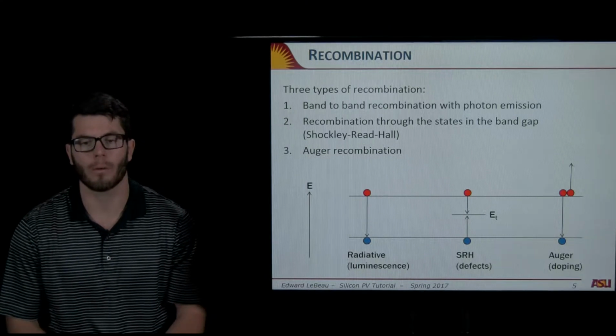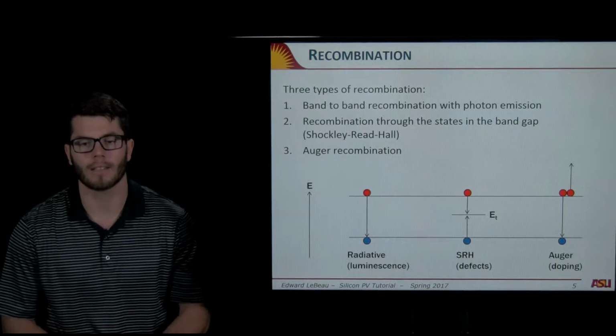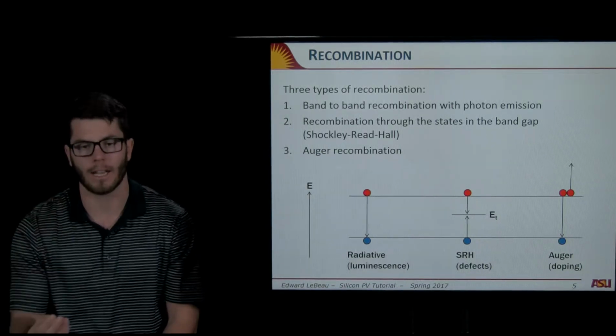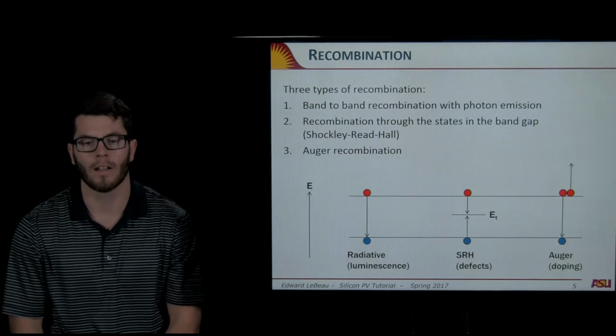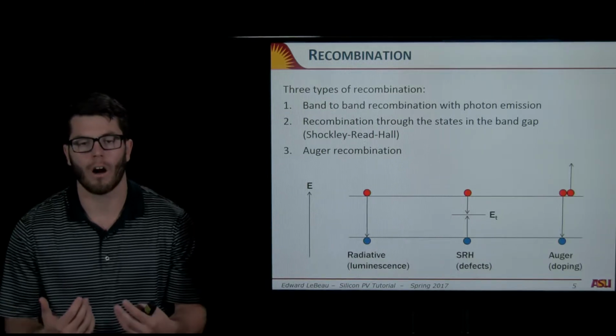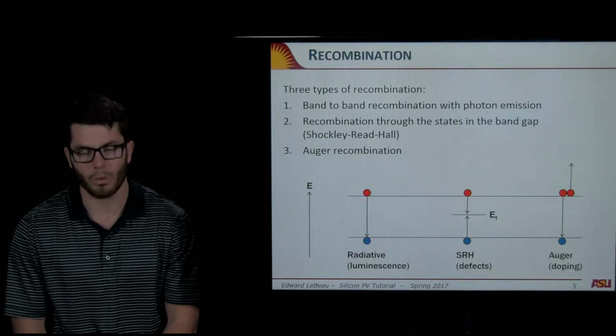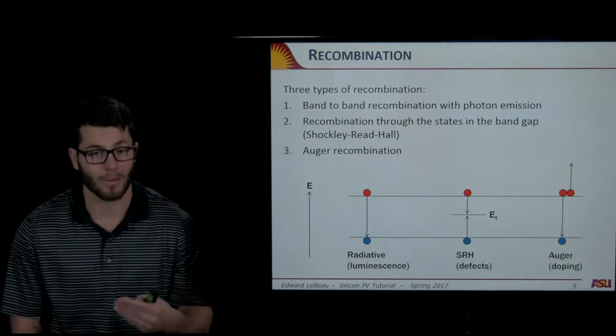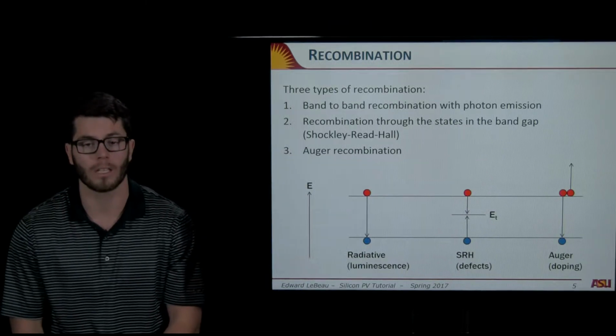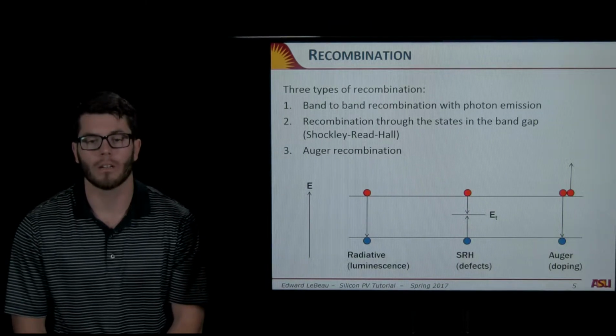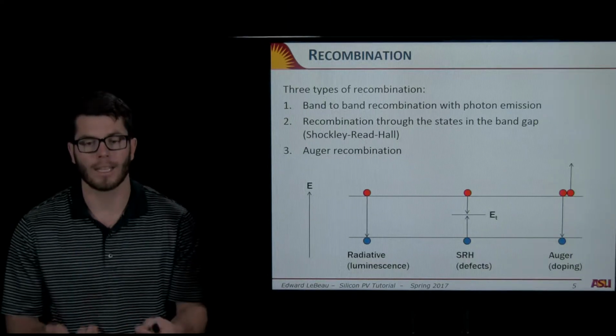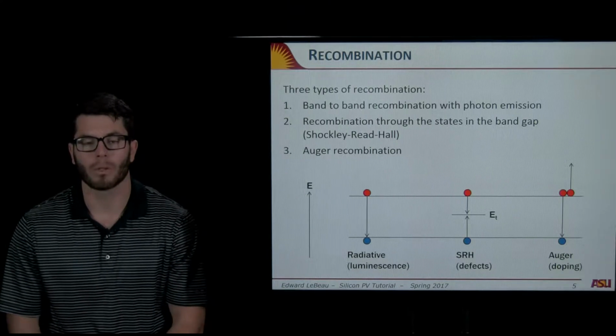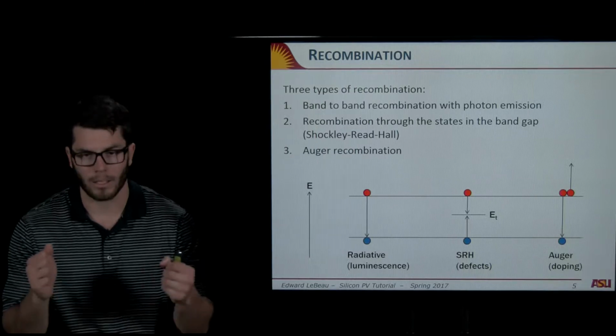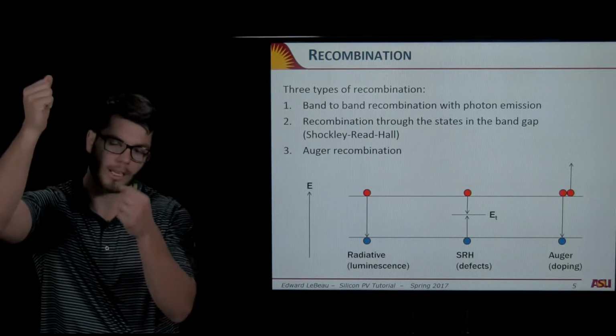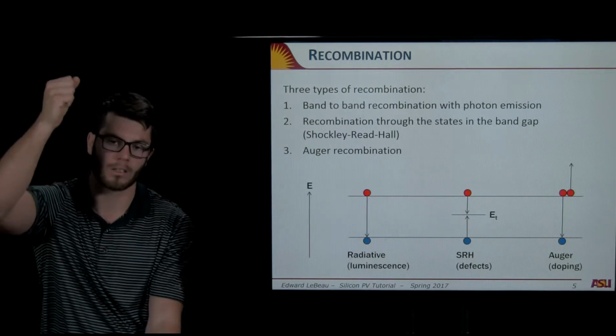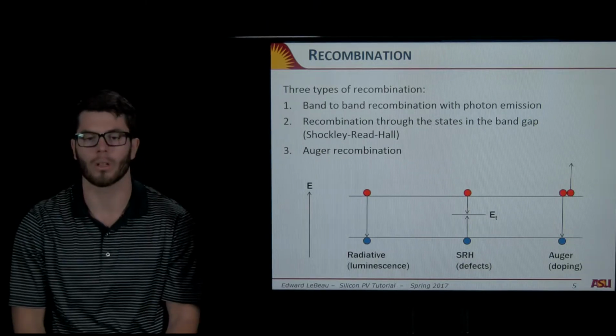But before we do that, let's remember our 3 types of recombination. First is radiative. Remember, that's your electron gets excited, it takes too long to collect it, and then it de-excites and releases a photon or a phonon. And then we have Shockley-Read-Hall, SRH, which is due to defects. Remember, some of those defects are intentional because we need to dope the silicon. And then we have Auger, which is when we dope it a lot, and we have multiple electrons in the conduction band. They interact. One electron gets shot to a higher energy state, the other electron drops back down, and then you lose this energy as thermal energy.